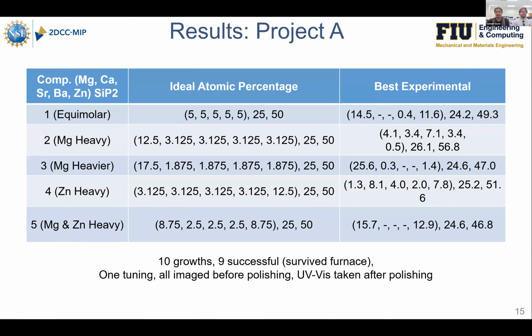For Project A, what you'll first notice is there are some dashes on some of the compositions. This just means that these elements didn't incorporate all too well into the crystals that we were able to recover. And even though some of them do have the whole gamut of elements, number 4 especially has all of them present, it's not really in the ideal atomic percentage that we wanted for that particular composition. We'll go on a little bit later to explain why we think that may not have worked,